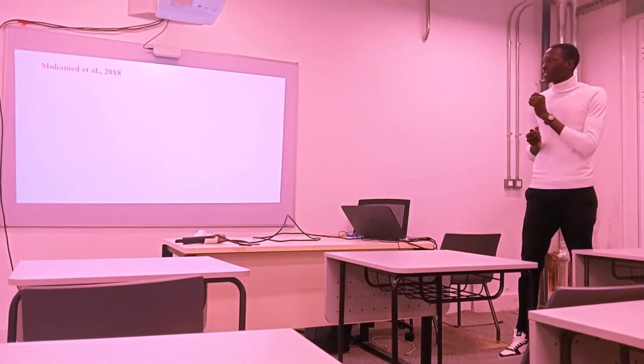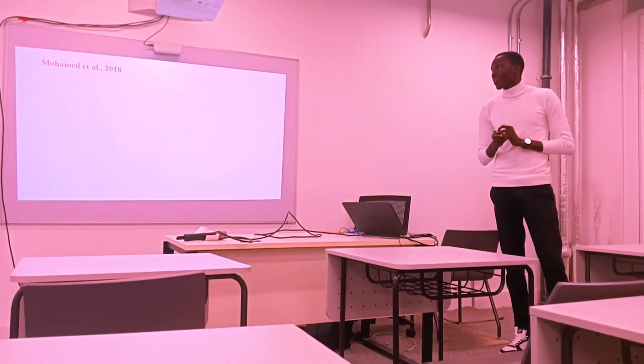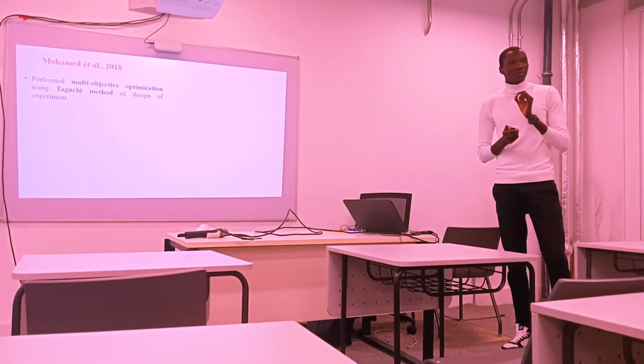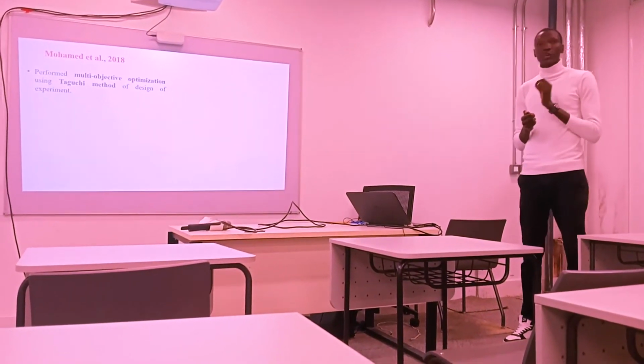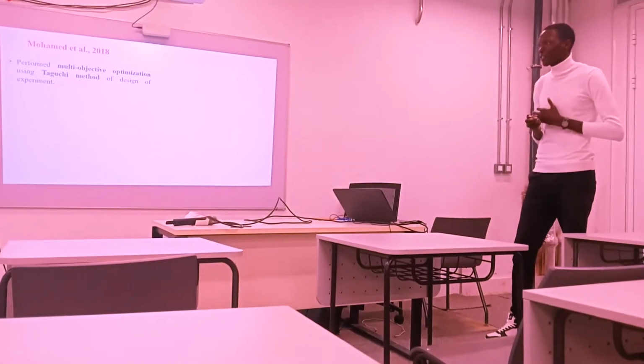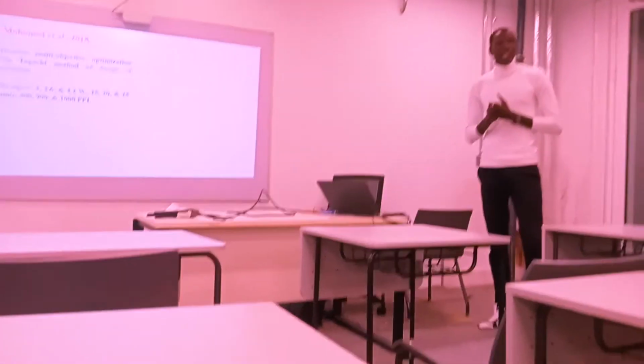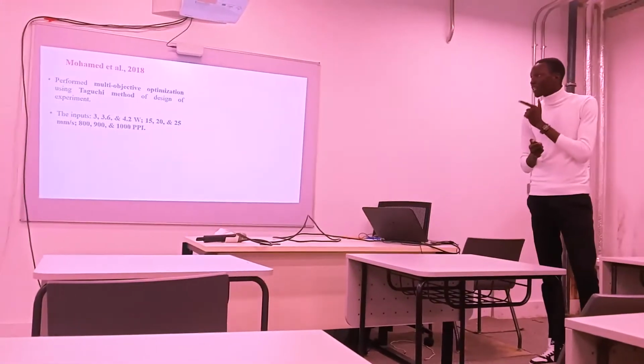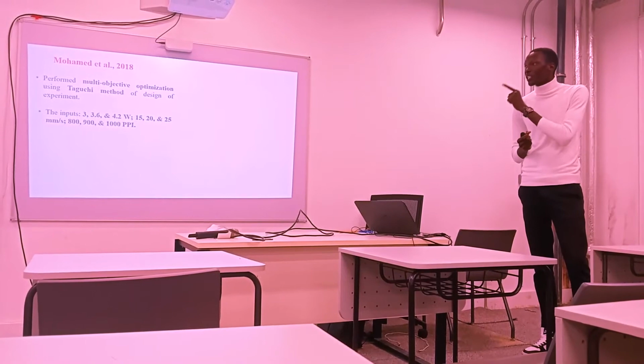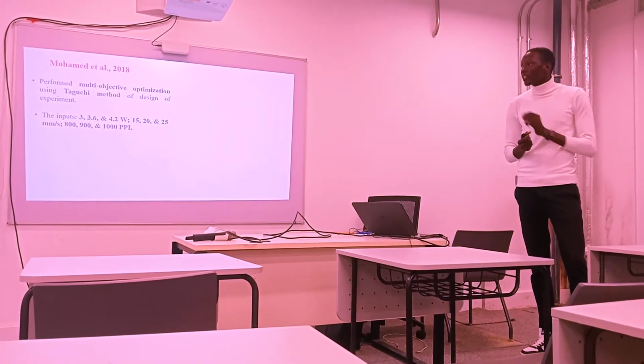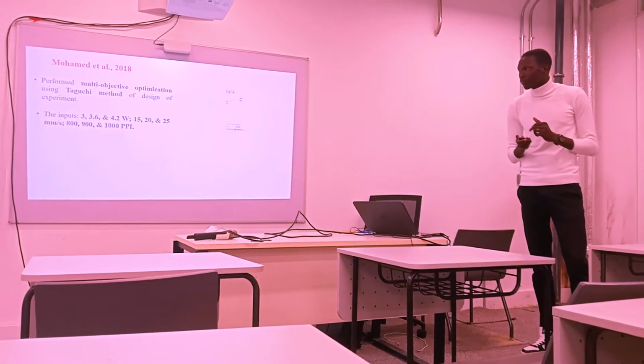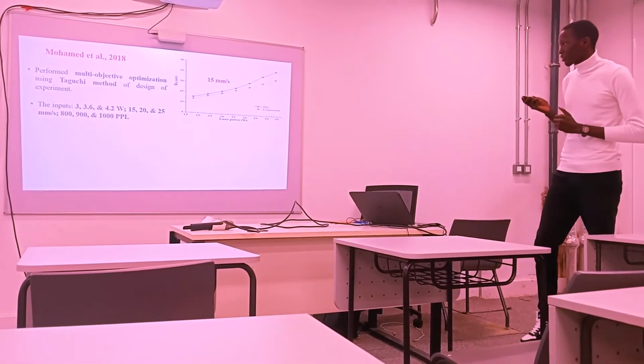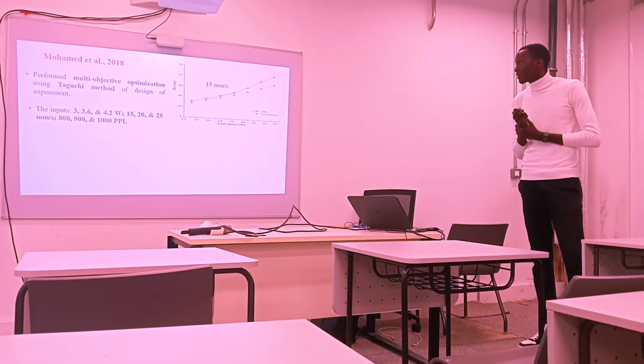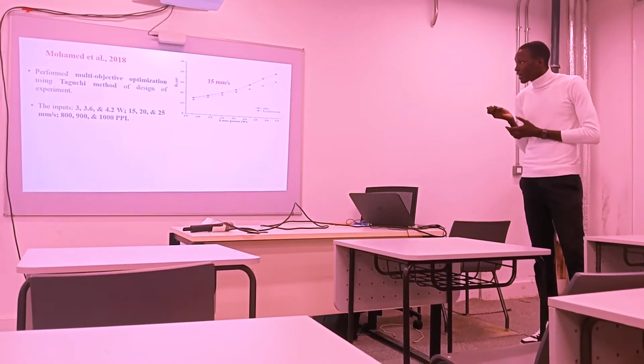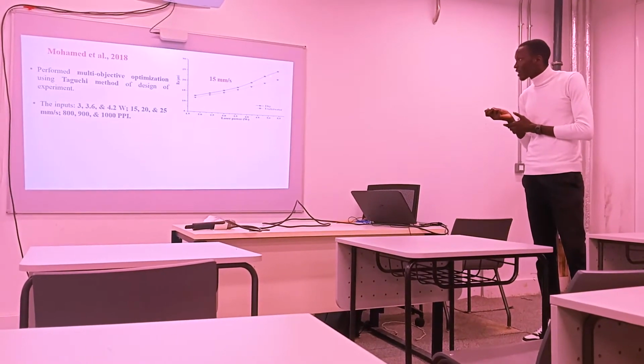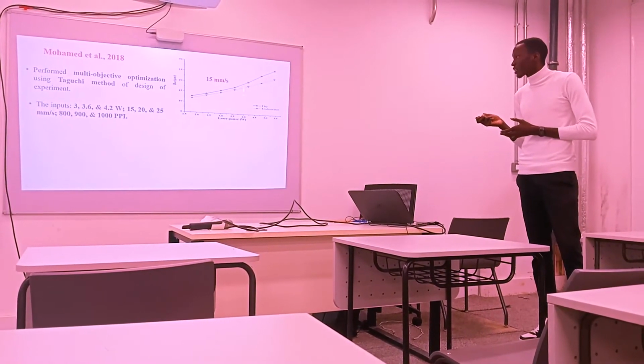In a progressive study, Mohammed and others conducted multi-objective optimization using the Taguchi method of design of experiments. The inputs were power 3 watts, 3.6, and 4.2 watts, speed 15, 20, and 25, and the pulse rate 800, 900, and 1000. This is what they got for surface roughness at 15 millimeters per second, in air, which is the red line, and underwater, this one.